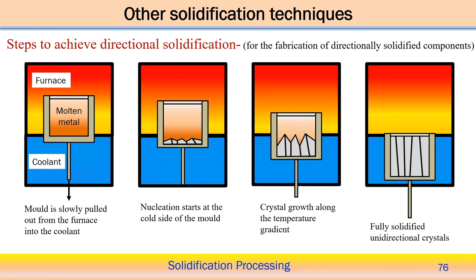Now, here we can better understand the steps to achieve directional solidification and for the fabrication of a directionally solidified component. In principle, in a simple way, there is molten metal, and on one side there is a furnace, and on the other side there is a coolant. So one side is heating and the other side has the coolant. Both control the direction, making it possible to control the temperature gradient or cooling rate. The mold is slowly pulled out from the furnace into the coolant. This is step one: the molten metal is gradually moved towards the coolant.